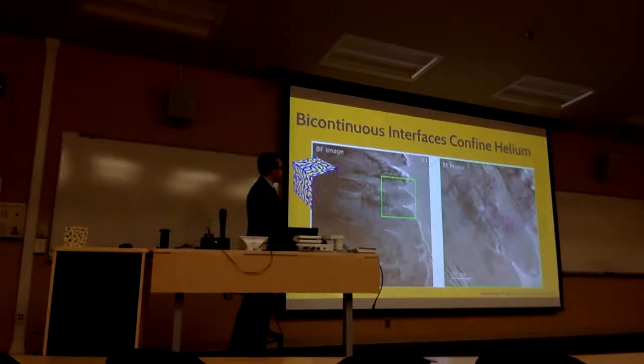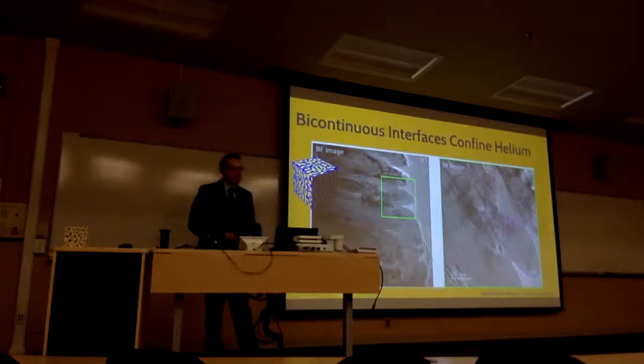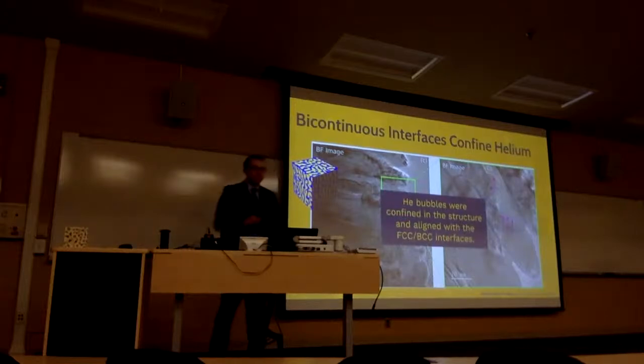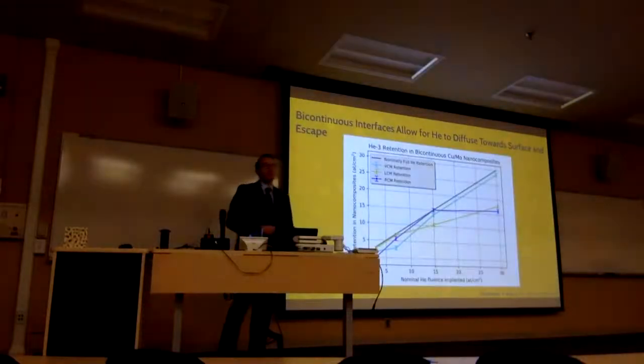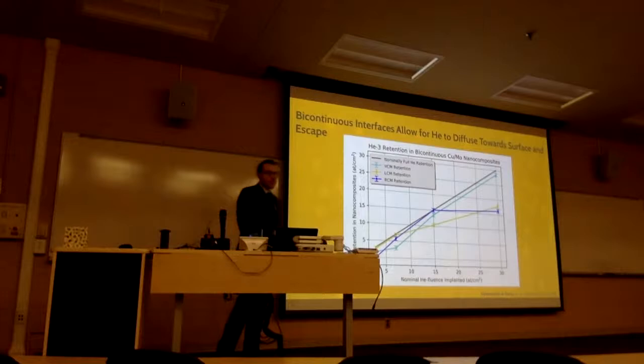So this is the bicontinuous structure, and I've blown up this image here in bright field. Hopefully you can see that the structure is littered with helium bubbles, but the helium bubbles, as pointed out by these pink arrows, inside the blue moly-rich and copper-rich domains, confine themselves to the FCC-BCC interface. So these helium bubbles do behave like inside the copper multi-layer design, and confine themselves to the interface. And if we map out helium retention in the sample as a function of dose or fluence, we can see that we have allowed some of the helium to escape through the material surface.